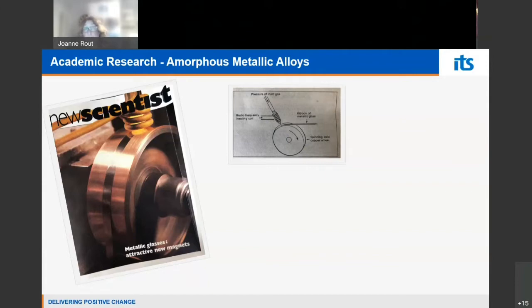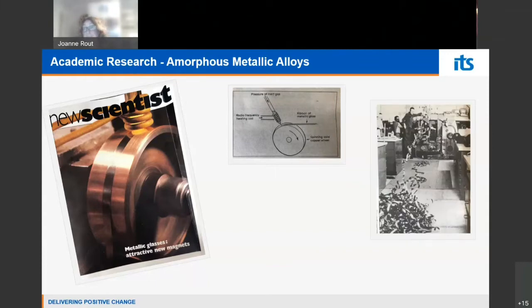Obviously, you can't do that with pure metals. It has to be an alloy, and the typical alloys we worked with were iron, nickel, and cobalt with a small amount of a metalloid, which is boron, silicon, or phosphorus. And that's what it looked like. It's a picture not from my lab, from a lab in America, from the New Scientist magazine. But that's actually what it looked like when I was spinning the metallic glass across the lab. Quite exciting. I didn't make metallic glasses quite this volume or thickness as part of my research project, but it was interesting.